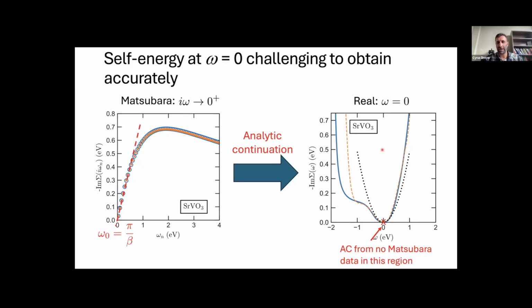And even if we do analytic continuation, where we can just evaluate the self-energy at 0 frequency, 0 real frequency, what I'll argue and I'll show later is that in this low energy regime, we are analytically continuing from a Matsubara self-energy that in that regime has no points. So in some sense, we are also extrapolating when we take this value of 0 frequency self-energy.